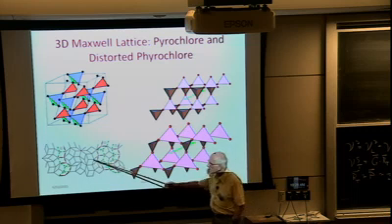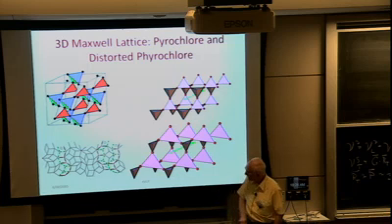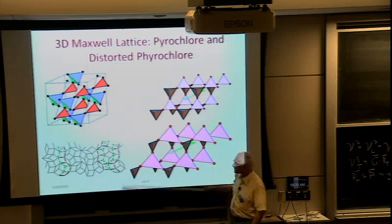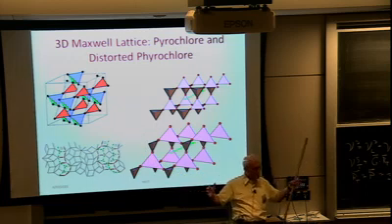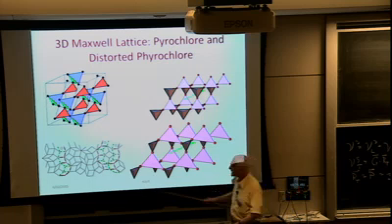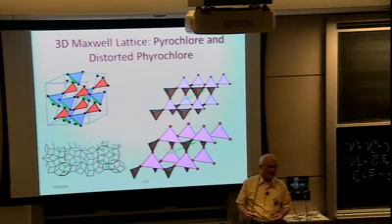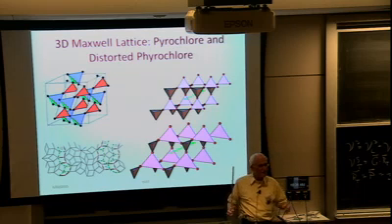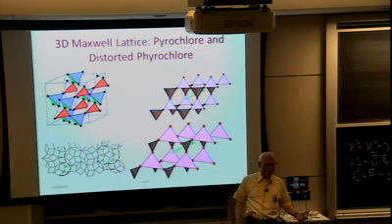If you look at this lattice, this is a rational approximant to a quasi-crystal. It's nearly random. It has, on average, 6 bonds per site. And if you take the limit where you go to a complete quasi-crystal, you have something that is elastically isotropic. So if you now randomize these positions a little bit, it's a good model for a jammed system. And it turns out that all of the properties of this system are almost identical to what you get for a jammed system.